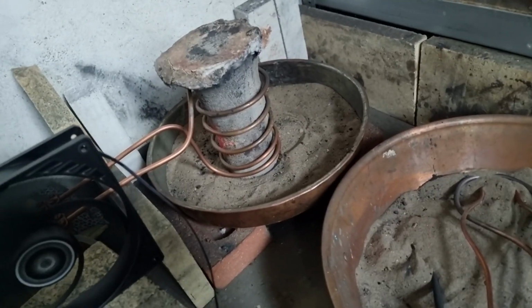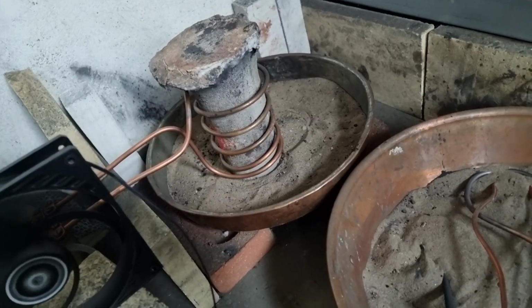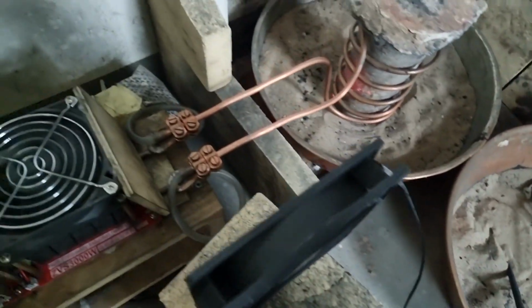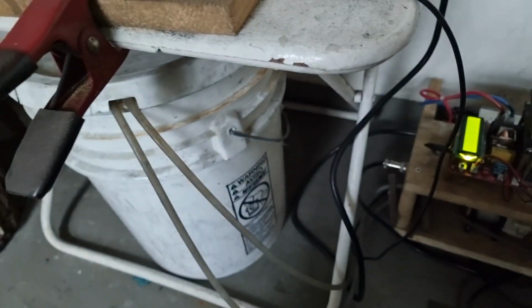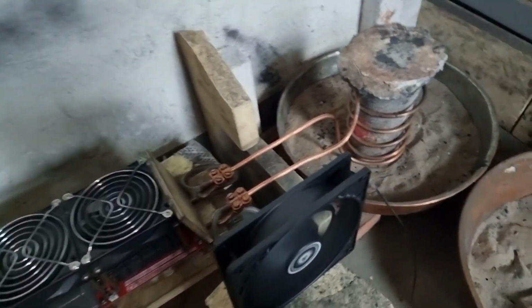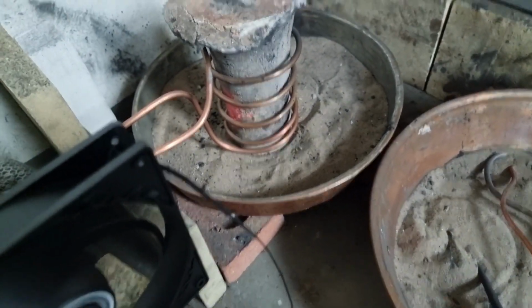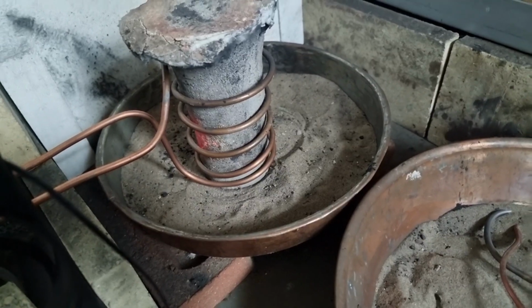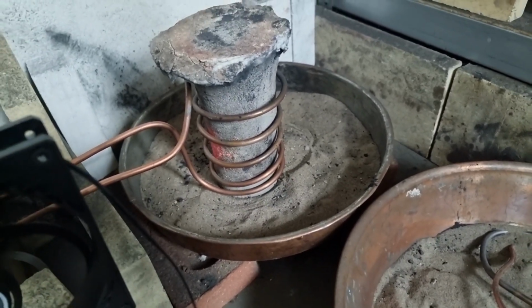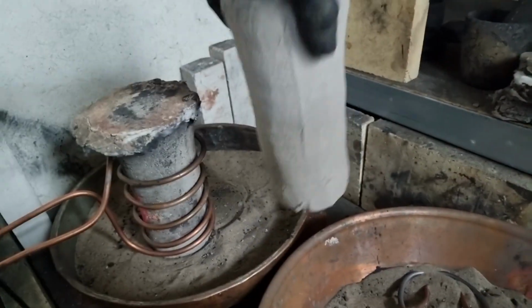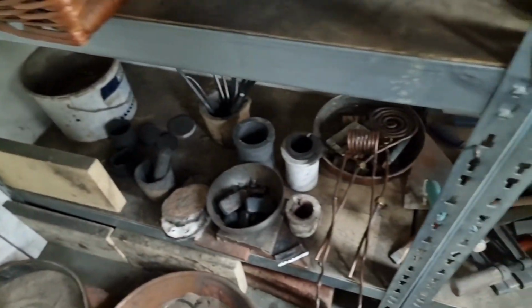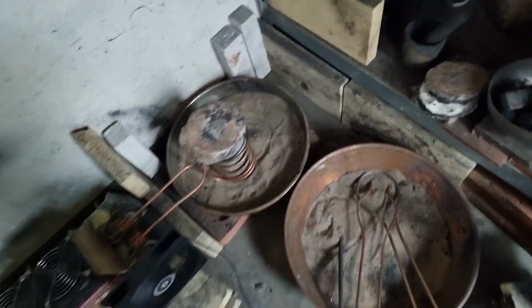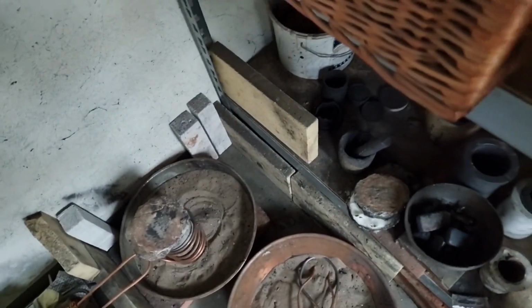Then put that all in your coil. You see that is a 6 millimeter copper tube, water cooled, so the water is flowing through that. On the inside we got here a 5-gallon bucket with water that is sufficient to cool that. You see there's some temperature coming through, but that won't matter that much. Then, 5 or 6 turns on that coil, and then you put your crucible in that coil and fill it up with your white cast iron mixture, and then you're gonna heat it up for, that took about 20 minutes or so.